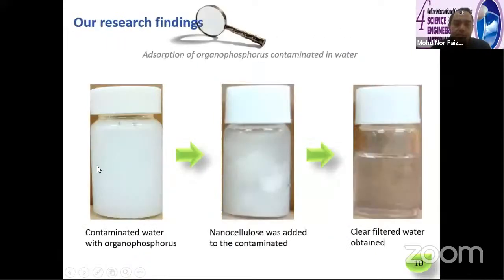We can see this contaminated water in white color, and then I added nanocellulose for a certain period of time, and after the water got filtered, we got clear water. So I tested the GCMS of this filtered water. We found that the organophosphorus can be removed totally from the contaminated water by using nanocellulose.